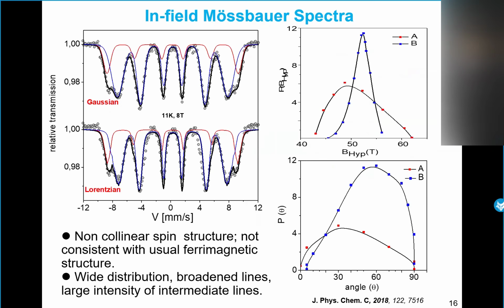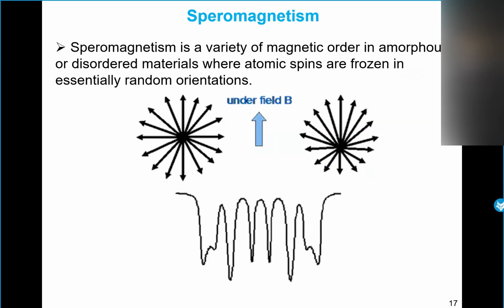So we have the inverse of the order of the intensity. For that, it is not possible to reproduce this experimental spectrum using just one subspectrum corresponding to the ferrimagnetic structure. We arrived to reproduce this spectrum using two subspectra corresponding to two speromagnetic-like structures with opposite hyperfine fields. So we have two speromagnetic structures antiferromagnetically coupled.